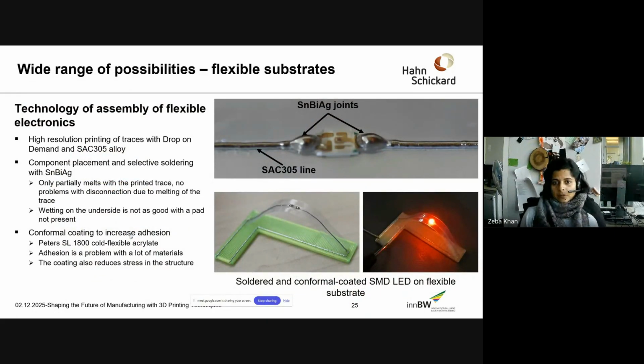The next wide range of possibilities is also in flexible substrates, because we can print the lines from the SAC305 metals, as mentioned previously, with the help of drop-on-demand technology, and then we can selectively solder them with the help of the low melting point alloy. This is a very good combination that was tested here, which can present a nice direct soldering of components for flexible electronics, as you see here in the image below. The green is the FFF printed polymer with some metal traces, interconnecting a flexible substrate with an LED on the top.